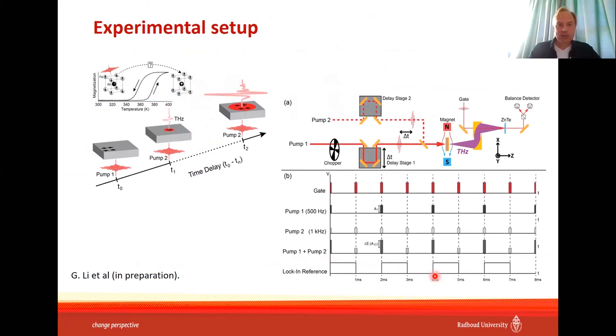This is how the system looks. You see two sequences of pump pulses at two different repetition rates, and then we detect only the signal that depends on pump one and pump two together, and the signal is in the THz emission that comes after pump two. First, there are no ferromagnetic nuclei, then pump one induces ferromagnetic nuclei, then we send pump two and detect THz emission from the nuclei induced by pump one.